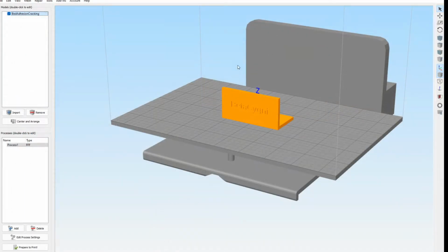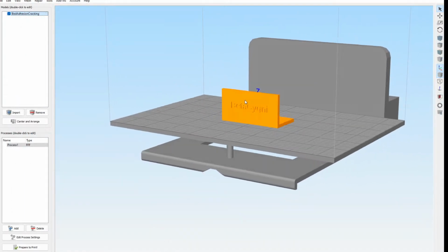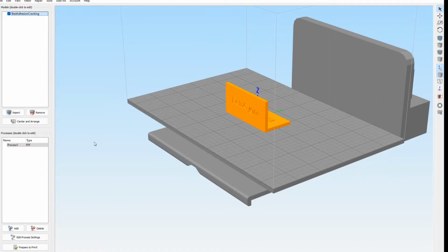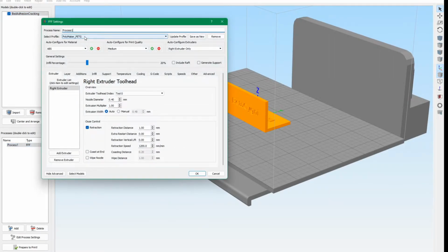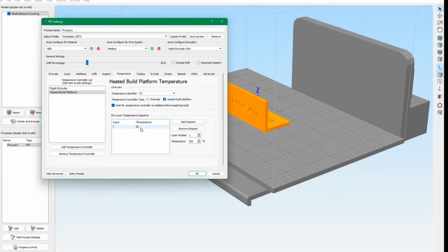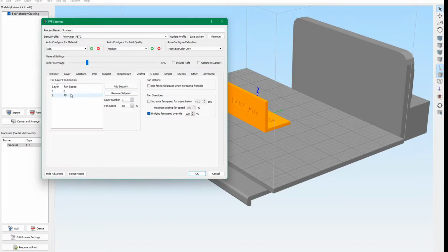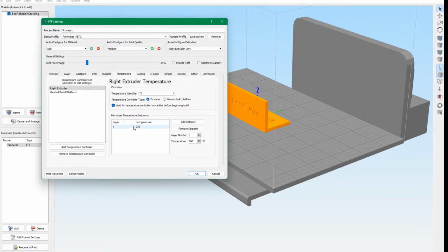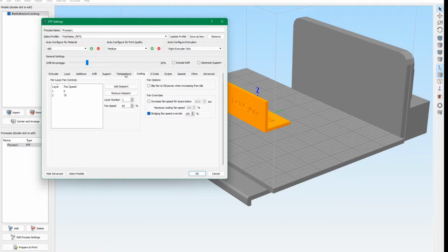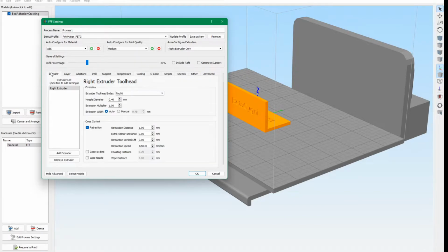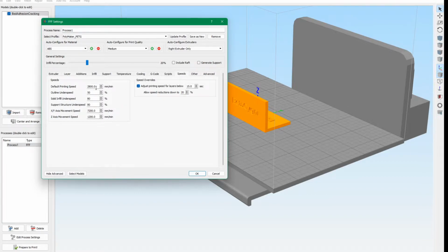All right, so here we are in Simplify 3D with our bed and layer adhesion and cracking test. And we've got our profile set for PETG Polymaker. And for temperatures, we've got 65 and 239. Now, once the cooling turns on, I found that this is going to be a couple degrees lower. So we'll see how it works out. The other thing on PETG, I use an extrusion multiplier of 1.0, whereas PLA I use 0.9, which is the recommended number. On the speeds, I slow things down.